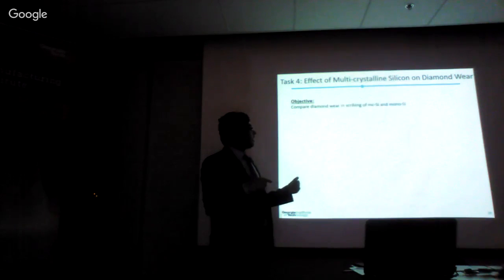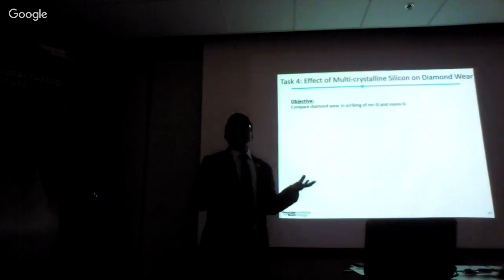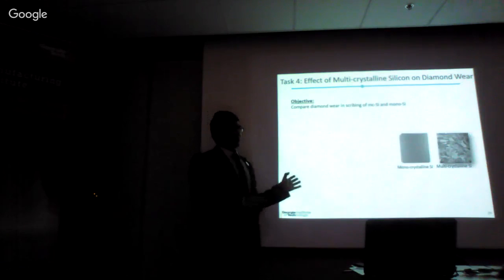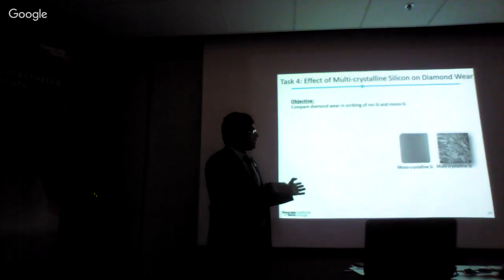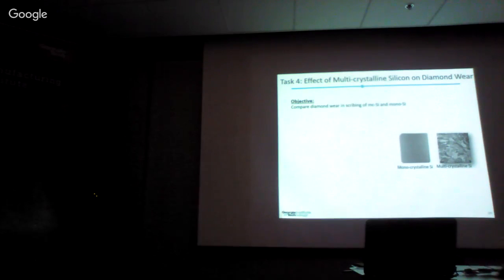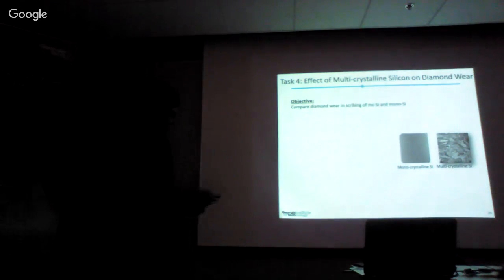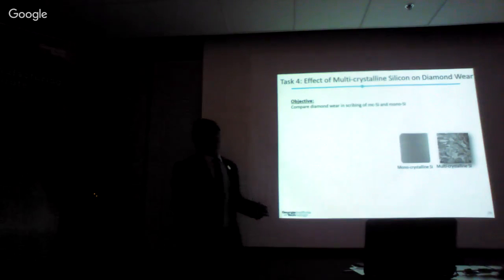Moving on to the effect of multi-crystalline silicon on the wear of diamond. This task addresses the challenge of why there is higher consumption of the expensive diamond wire when cutting multi-crystalline silicon compared to monocrystalline silicon. To compare that, we revisit that multi-crystalline silicon has a lot more grains and twin boundaries, as we found in our previous task, compared to monocrystalline silicon. And I'll pass around the two samples with the indenter which I used in this experiment. And you can see the scratches made across the grains and twin boundaries.